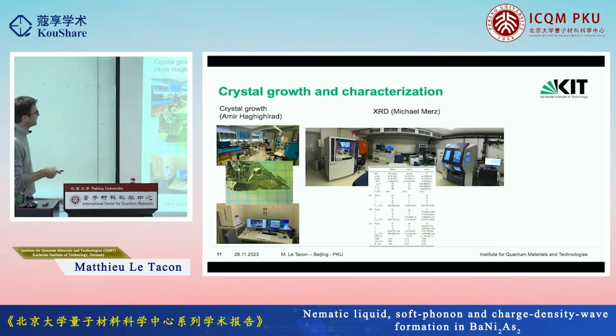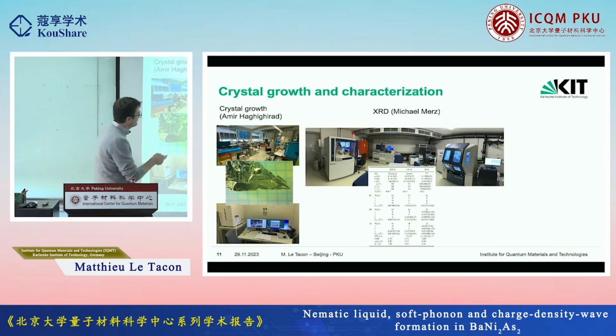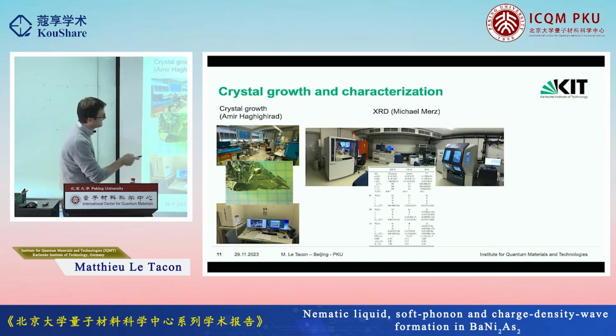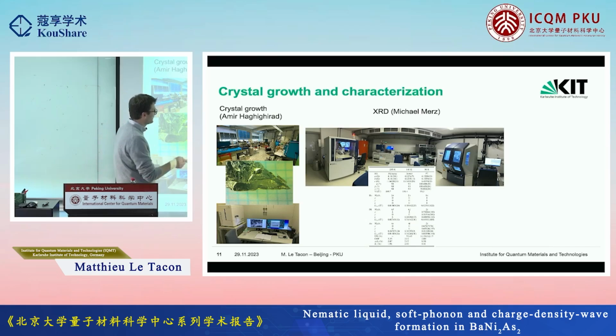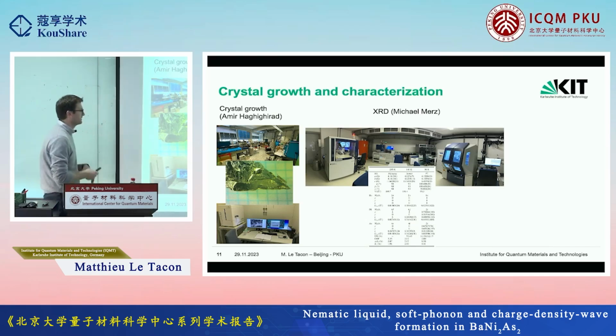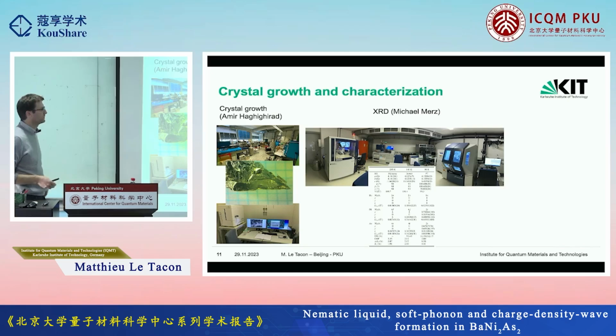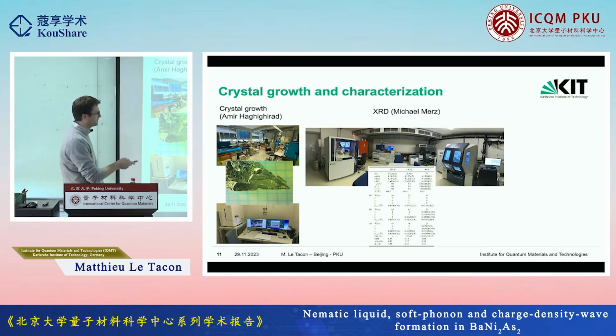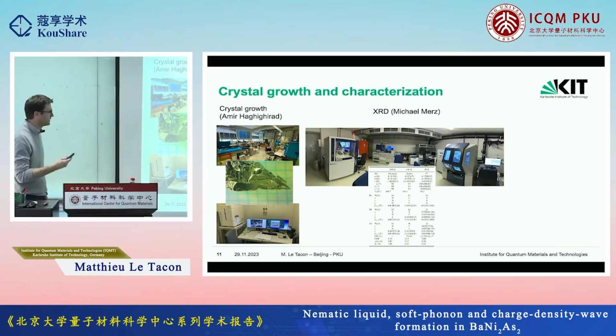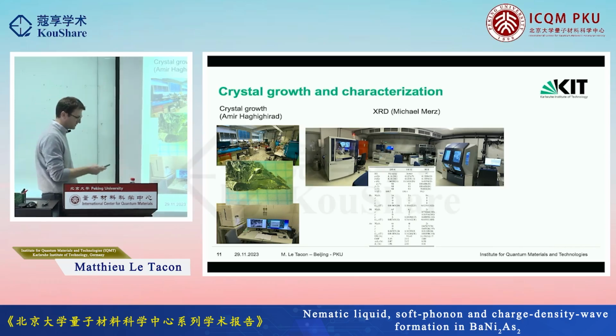We recently refurbished our X-ray lab, so this is only part of it. We have this four-circle diffractometer. This is the new beautiful Synergy Rigaku machine. That's the one I was talking to you about. It's just fantastic, and a SmartLab for the powder diffraction. So that allows us to work systematically, and actually for all the crystals we look at, we always start by checking that the quality is good with X-rays, and make an actual real crystallographic refinement to really know what we are looking at.